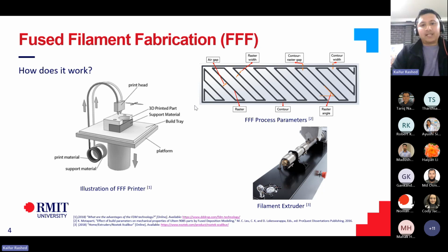This is part of the study that I did, where I optimized the properties of printed parts by changing the process parameters. And I also used a filament extruder because I developed my own material. So I had to mix additives with polymer and then extrude them to make a spool of filaments.